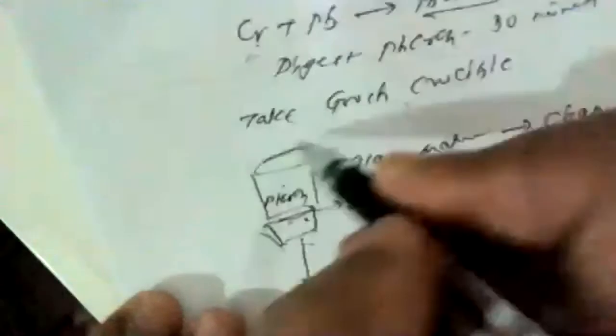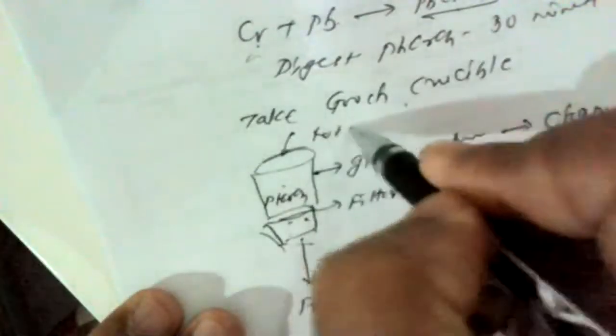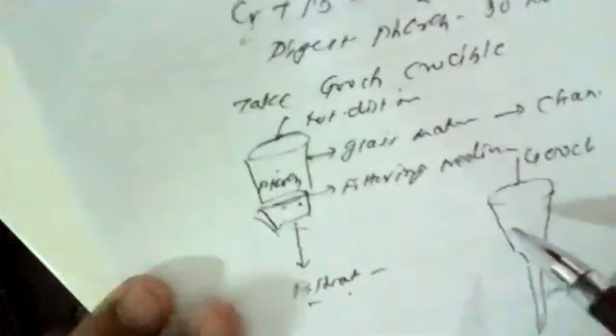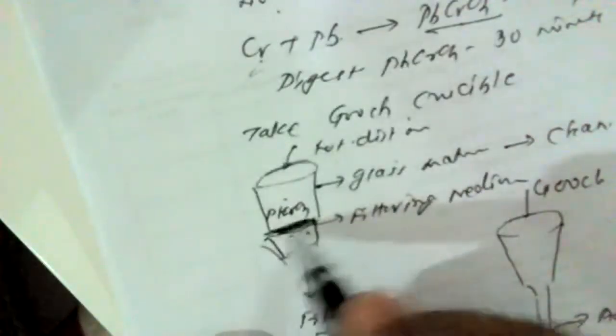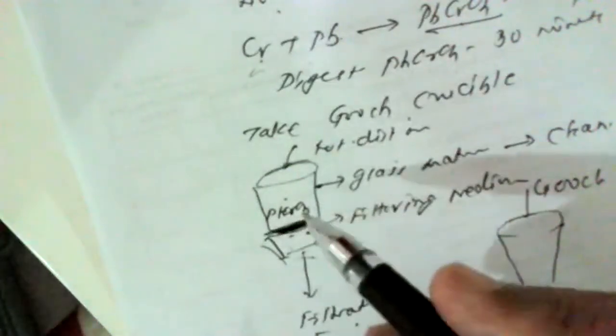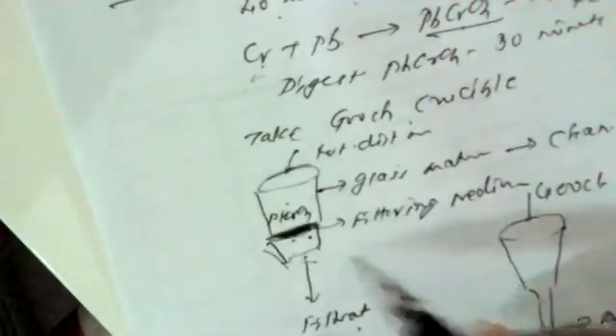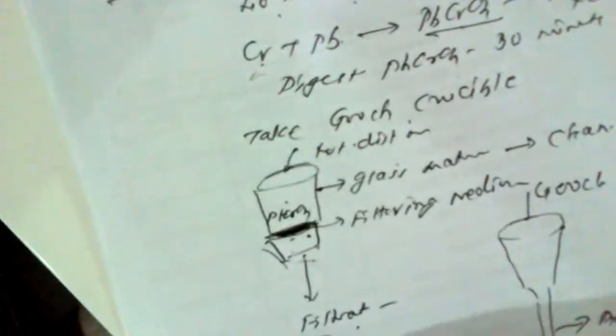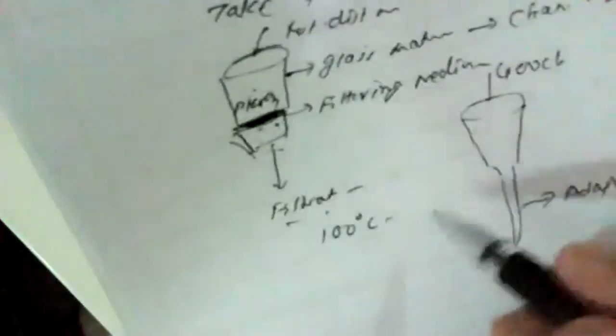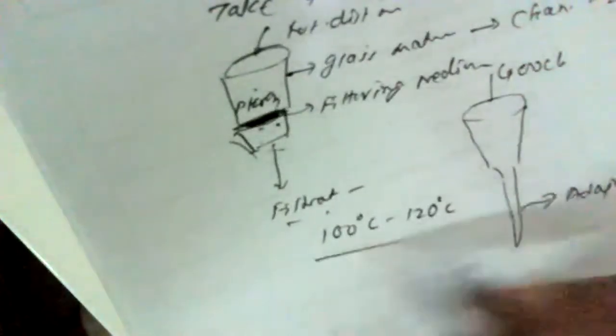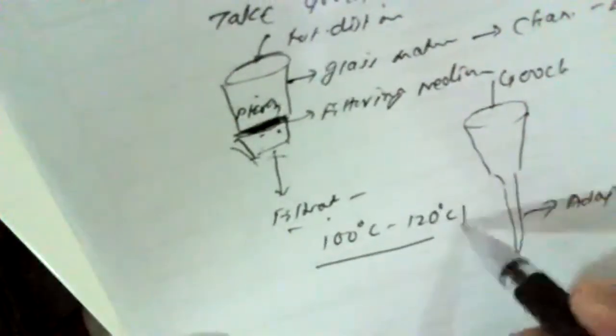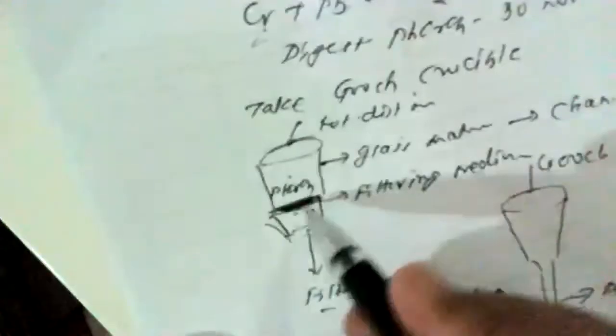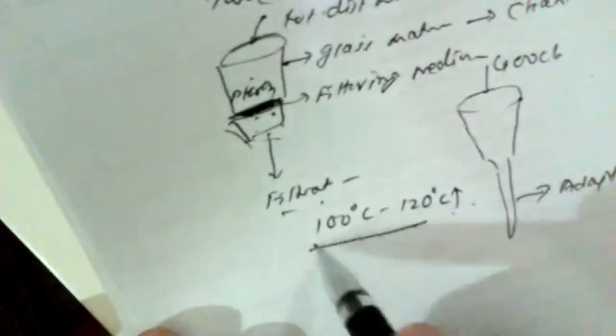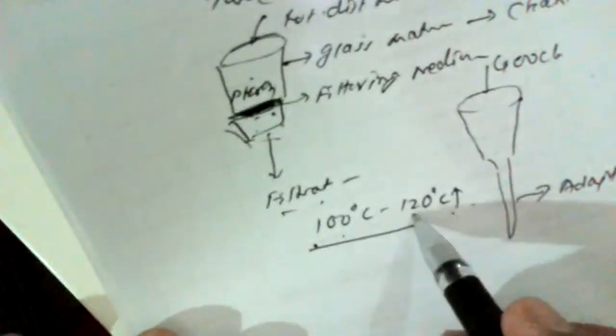And we have to wash this precipitate with hot distilled water also. After complete transfer of this lead chromate precipitate, very fine yellow colored crystals are obtained. Now this crucible is to be kept in an electrical oven, and the temperature should be maintained between 100 to 120 degrees centigrade, because if we increase the temperature beyond this limit, the filtering medium may melt. So care should be taken that the temperature is 100 to 120 degrees centigrade.